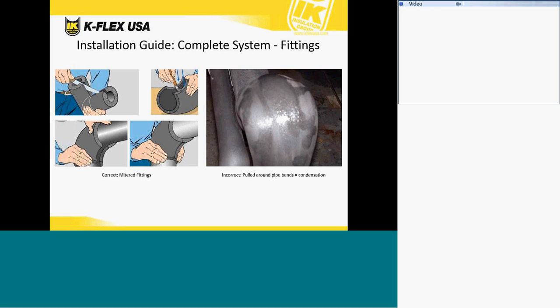For fittings, there's a complete guide showing how to create mitered fittings for all types and sizes of piping. On the right side, you can see an incorrect installation where the pipe is pulled around a very sharp elbow here. That causes the insulation to thin out around the elbow, which would lead to condensation and wear and tear on the insulation, and it will eventually fail.